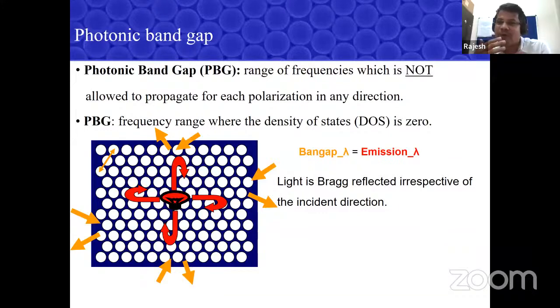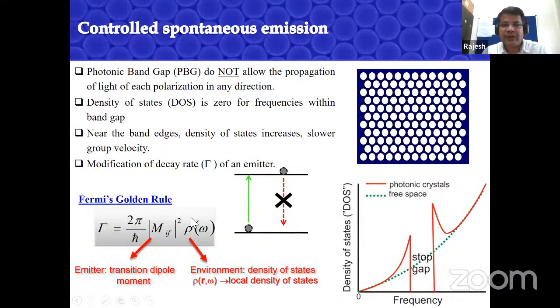or nanophotonics became extremely popular, because now you have a very nice dielectric system where spontaneous emission can be fundamentally altered. Not only is it of interest in physics, but it also has a lot of technological applications, like highly efficient lasers, or you can make emission anisotropic, and make it in a very strong and particular direction. So if you look at a photonic crystal, the light you send from outside cannot propagate, it is reflected back. I keep the light source inside at the same band gap frequency. The light cannot propagate at the band gap frequency because it has internal Bragg reflection.